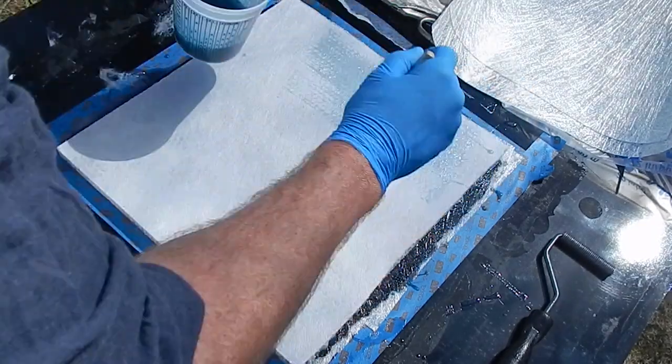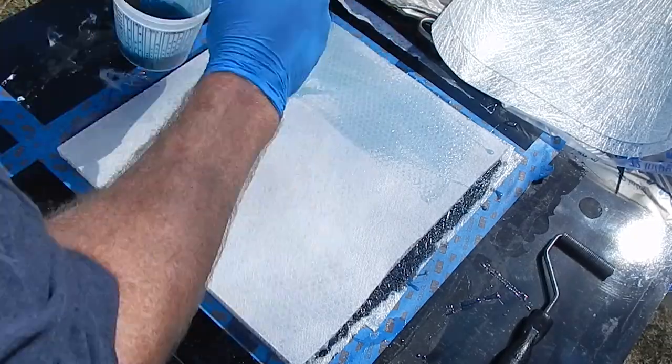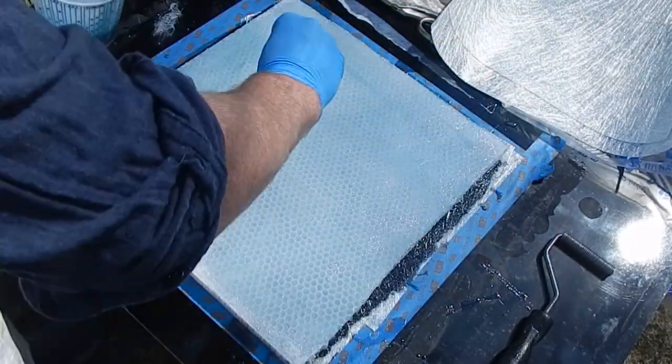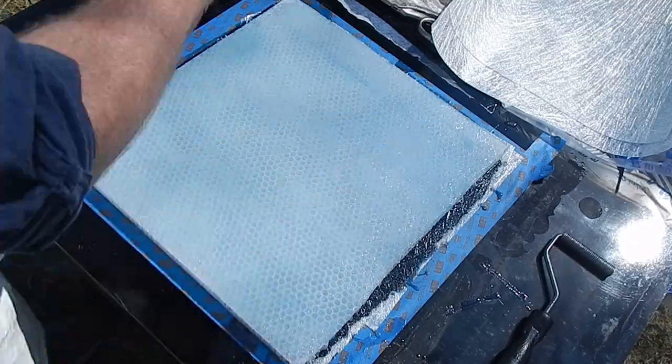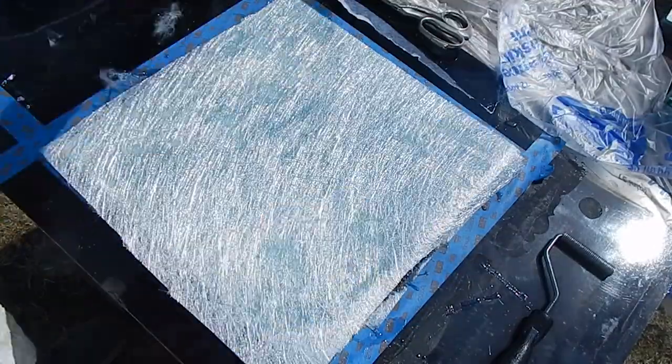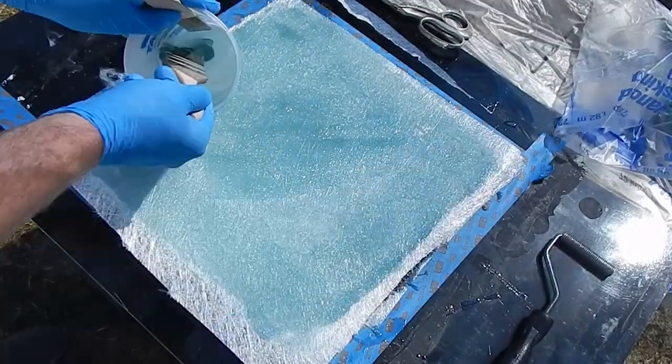So I'm catalyzing the top laminate here after the bottom is gelled. This is at 2%, a little bit hotter because this is not right on that hot black sheet.